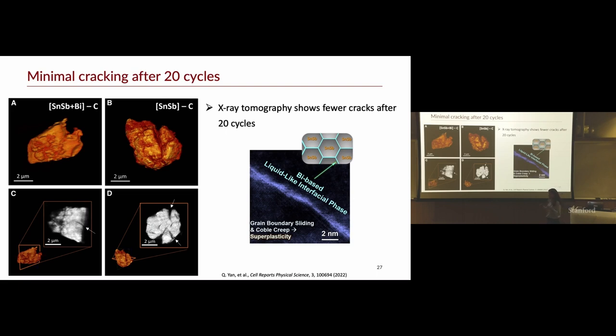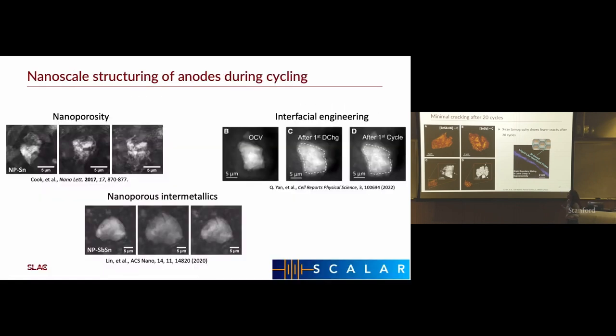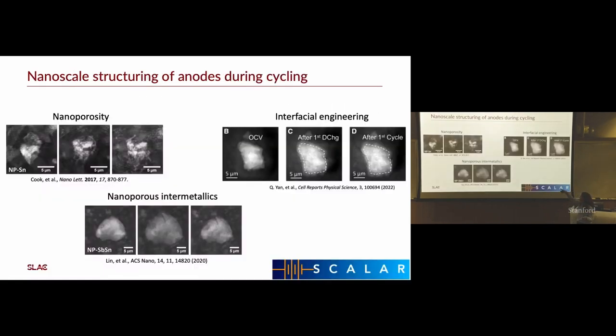And so with a combination of operando in situ 2D imaging and ex situ 3D imaging, you can really get a good idea of why the architecture that you're choosing is able to help mitigate the cracking and give you a long cycle life. So just as summary, we explored nanoporosity, which gave us the preservation of the total areal expansion, but destroyed the morphology.